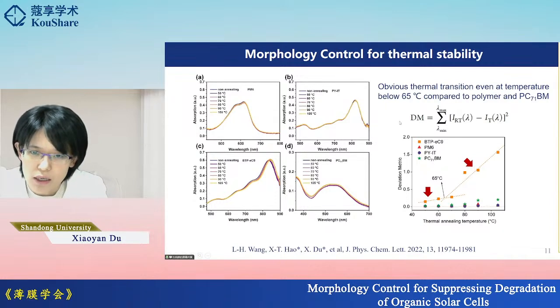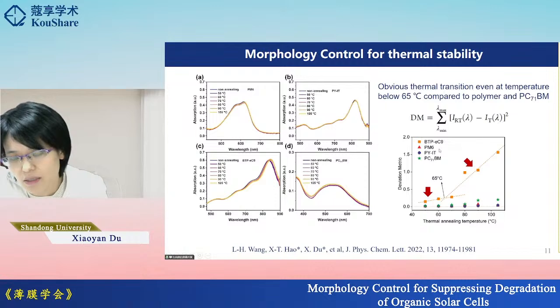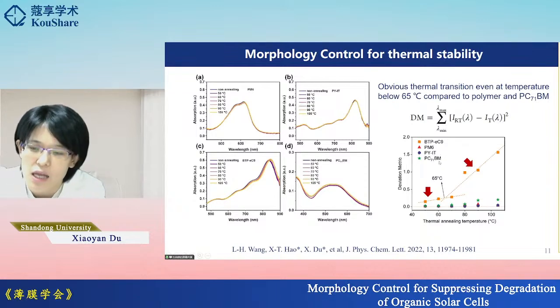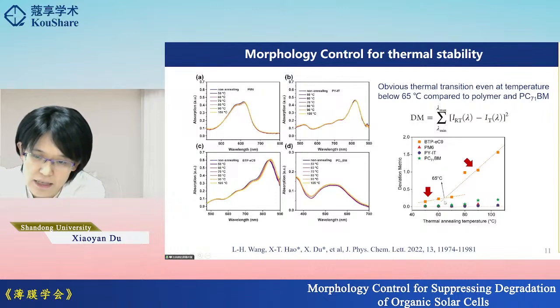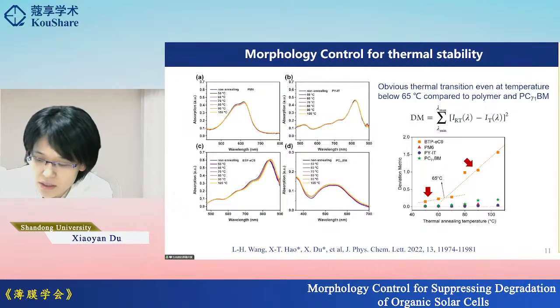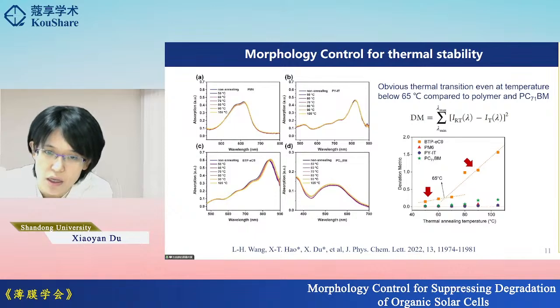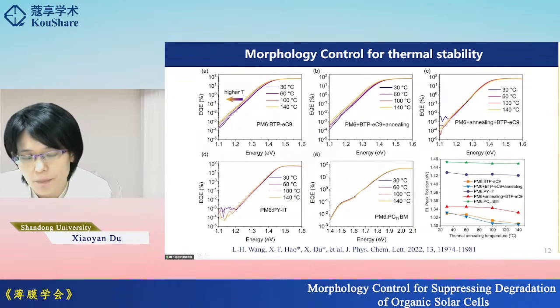And we also investigated one of the materials shown here and compared the thermal stability with the polymer donor PM6 and PYIT as the polymer acceptor, and compared with the fullerene derivatives. We show that even under this transition temperature here, around 65 degrees, even at lower temperature, they show a higher slope compared to other materials. And this thermal transition behavior is obvious in many other optical-based measurements.